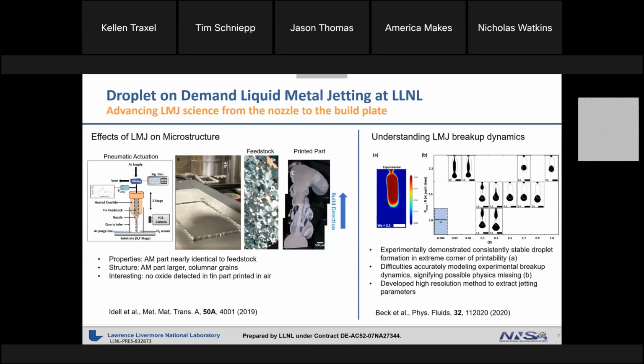And we found that the properties such as density and hardness of the printed part matched the feedstock very well. However, the microstructures were quite different. Feedstock had small equiaxed grains, while the printed part had large columnar grains that ran up through the build direction. Of interesting note was that we could not detect oxide within the tin part despite it being printed in air.